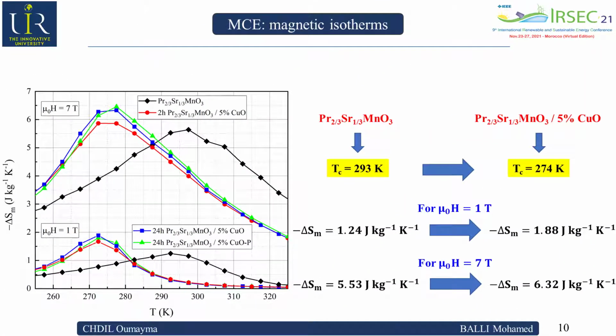The change in magnetic entropy as a function of temperature of the two samples is shown in the following figure. As observed, the highest magnetic entropy change for the composite approaches 1.8, while it's approximately 1.2 for the Pr1-xSrxMnO3 under 1 Tesla.